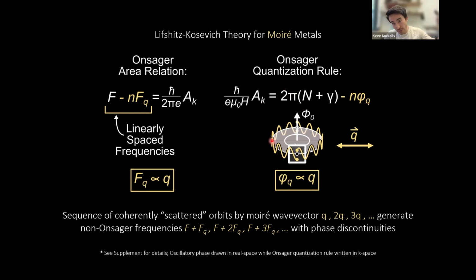And so the idea is that in real space, the electron is moving in its cyclotron orbit, and its phase comes to this so-called hotspot in momentum space, where the direction of propagation of the electron is along the Moiré wavelength. And so effectively, this electron can scatter and pick up some phase discontinuities by integer multiple scatterings of the Moiré superlattice, and then it phase propagates again. And then when it comes back around, it staircases back down the other way. And so it's 2 pi periodic with these phase discontinuities, although these look really strange.